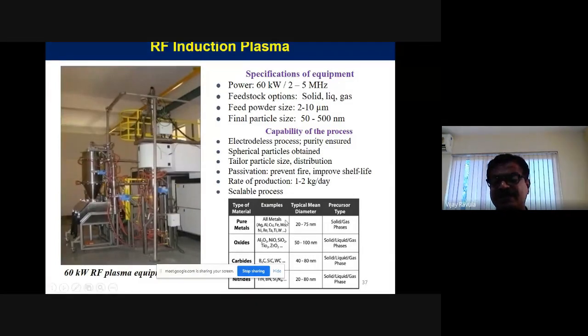So different pure metals you can make: silver, aluminum, copper, iron, various materials. The size is around 20 to 75 nanometers. And then oxides: alumina, silica, TiO2, all those things. You can also make carbides like tungsten carbide, silicon carbide, boron carbide. So these are all the things you can do. Even the nitrides, titanium nitride, boron nitride, silicon nitride, all those powders you can make using this process.